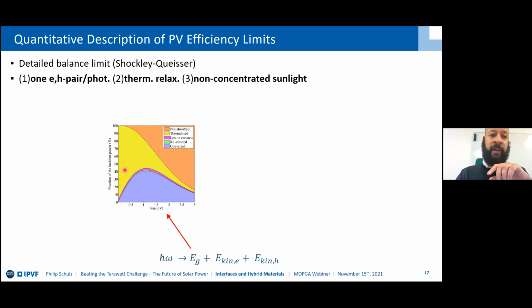And if you now make a very small band gap material, you see that a lot of this is yellow, and this means thermalized. So you lose a lot of energy to thermalization. And only this blue curve here is sunlight that is actually converted into electricity. In the very ideal case, there are some additional factors that contribute to an even lower fraction of power that you can get out of this. Silicon has a band gap here at 1 eV, giving us about 30%.